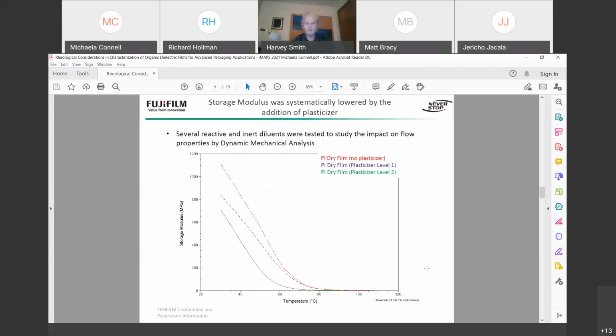So several reactive and inert diluents were tested to study the impact on flow properties by dynamic mechanical analysis. We selected this combination of diluents, which systematically lowered the storage modulus. As you see in this figure, we added two different levels of diluents, which decreased storage modulus as the amount increased. So here we have the first level of plasticizer of the diluents, and then we have the second level, which is higher, and both have systematically lowered the storage modulus.